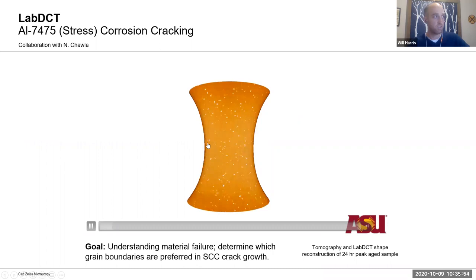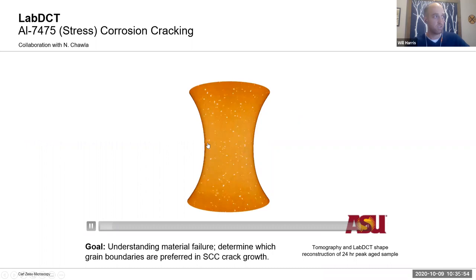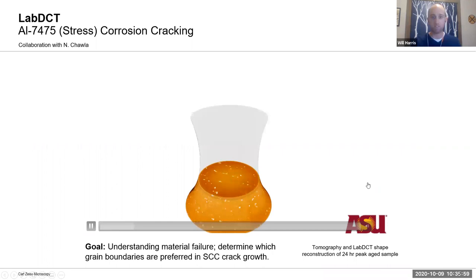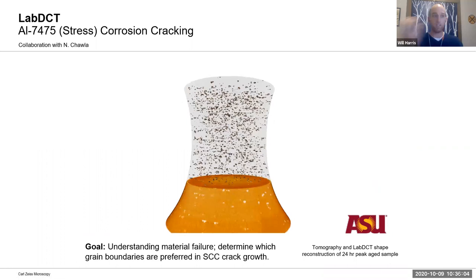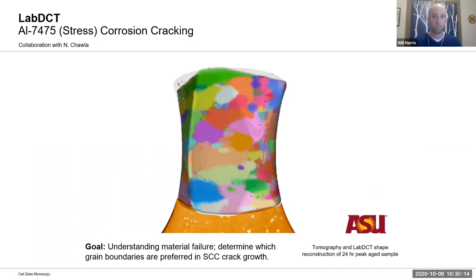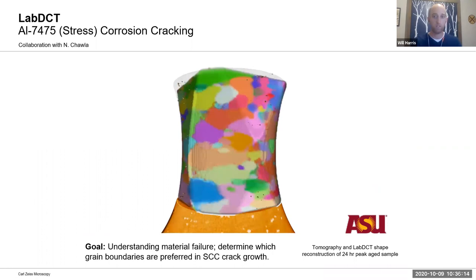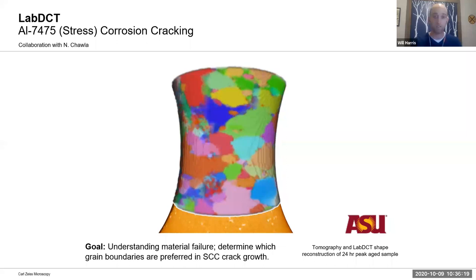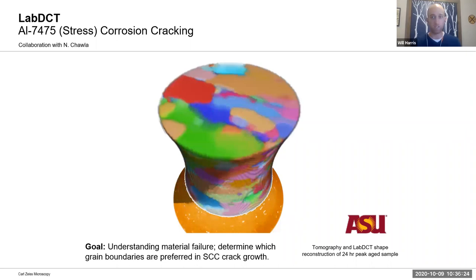So what we did was: we can still image the inclusions — all the little bright spots — but what if we also do diffraction contrast tomography to image the grain structure? Then we can overlay these two datasets, which are spatially correlated, and look at where the inclusions actually exist relative to the individual grains. This adds a layer of insight into the structure and the types of factors that may impact performance — whether corrosion, mechanical properties, or thermal properties.